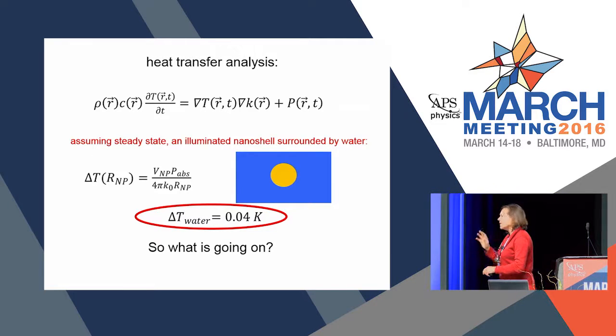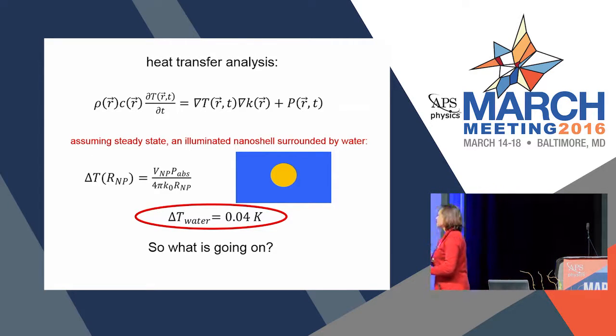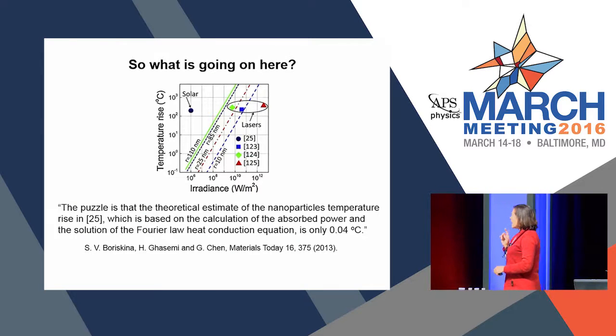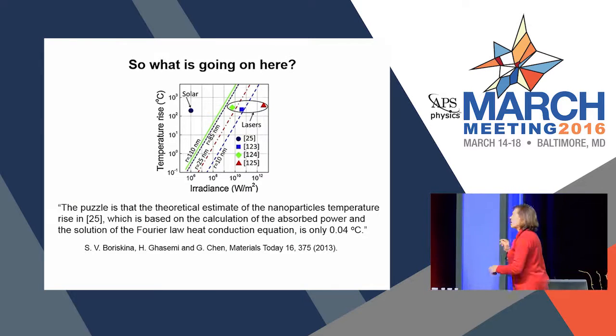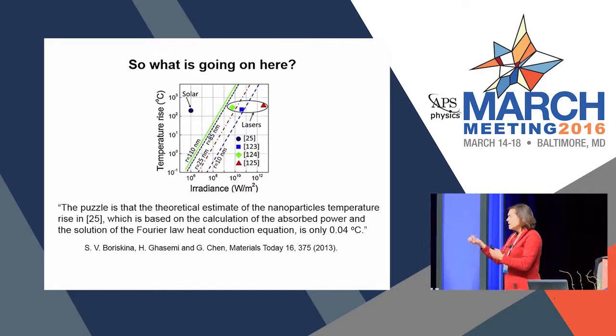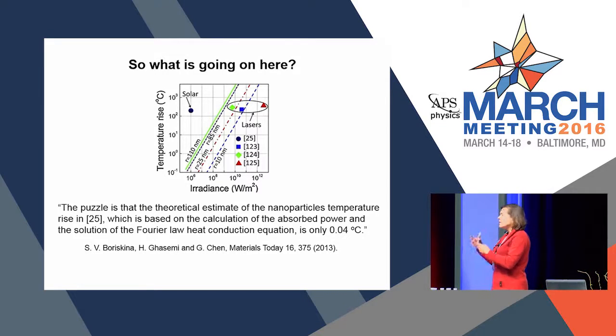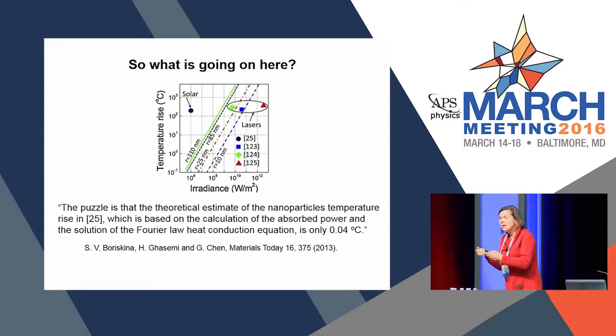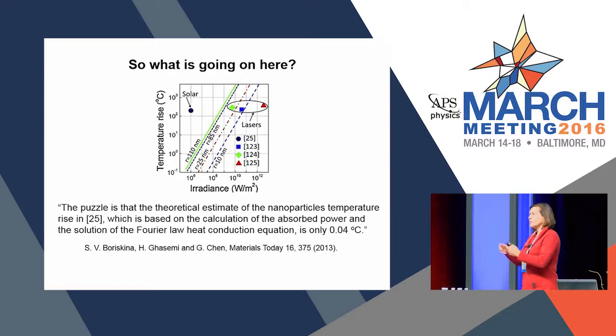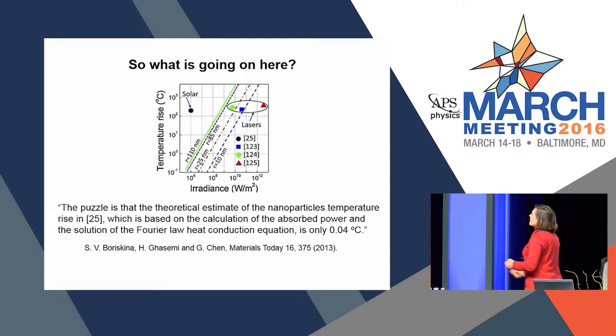Are we actually generating steam? And the answer is definitely yes. And we weren't the only ones who found this was very strange. We were doing individual particle experiments, and we found that the energy needed there for making a bubble around an individual particle was very different than what we were observing. And we weren't the only ones.